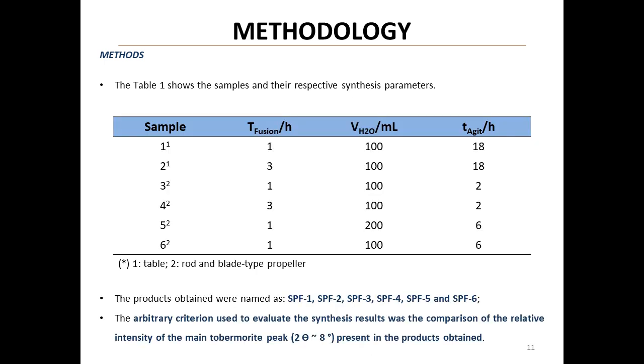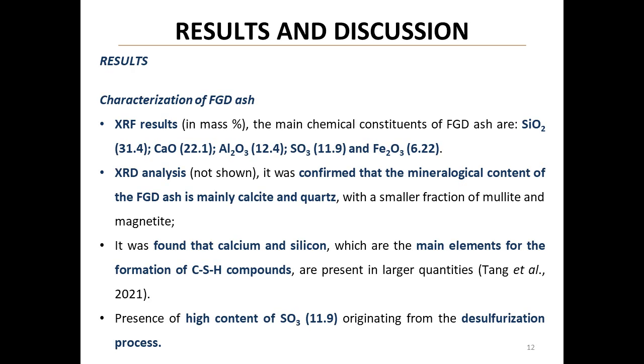The researchers tested different parameters such as fusion time, water volume, and agitation time to optimize the process. They named their products SPF 1 through SPF 6, evaluating them based on the intensity of the main tobermorite peak. Their results show that the FGD ash contains high levels of silicon and calcium, making it suitable for CSH synthesis. The presence of sulfur from the desulfurization process was also noted.